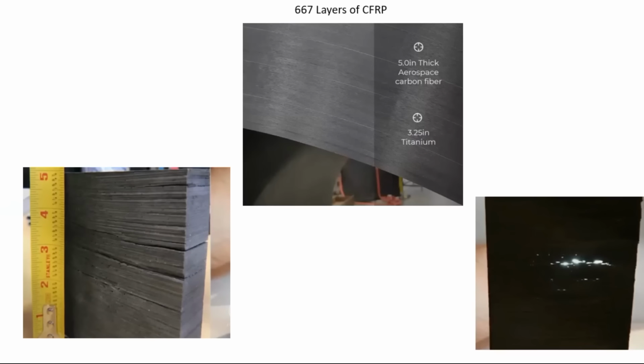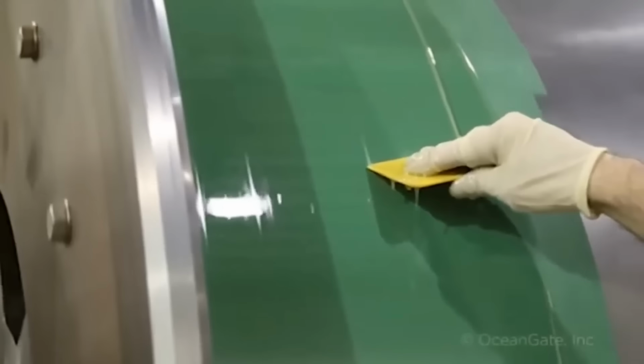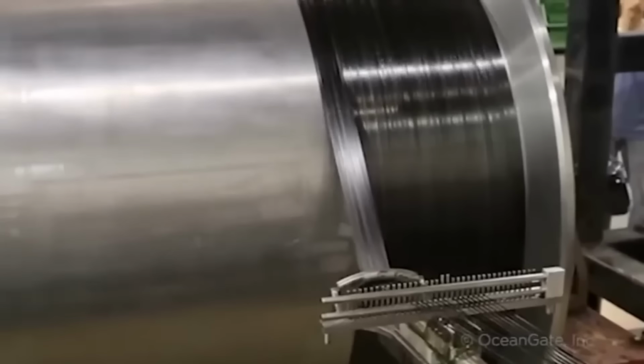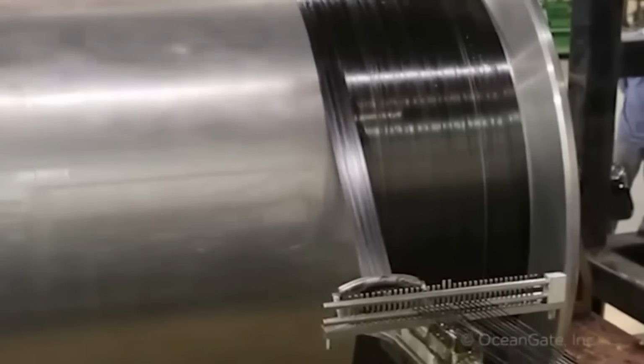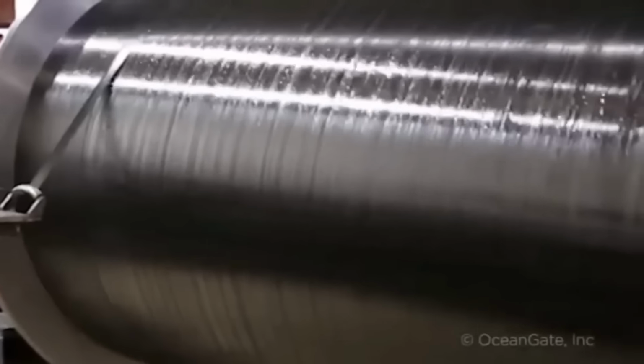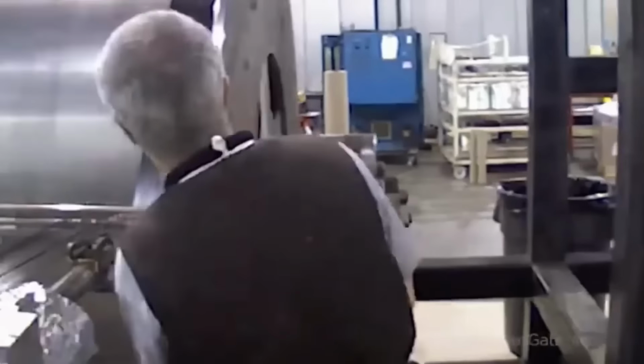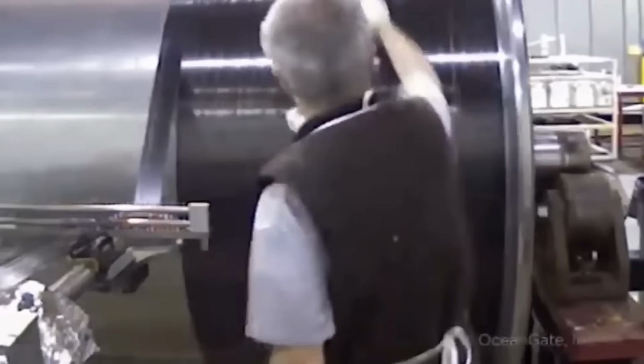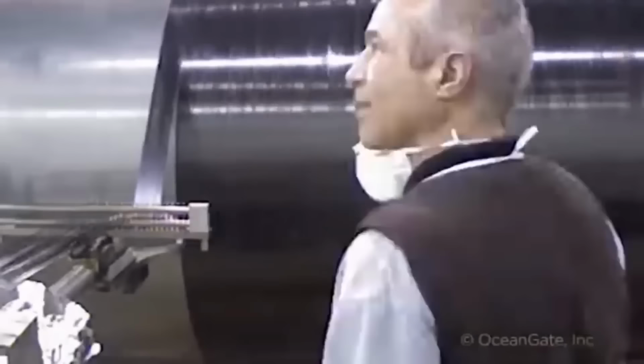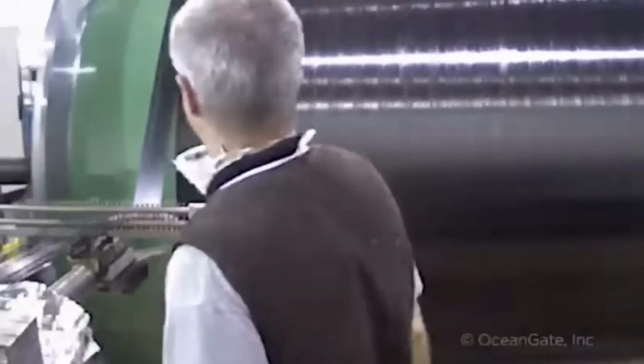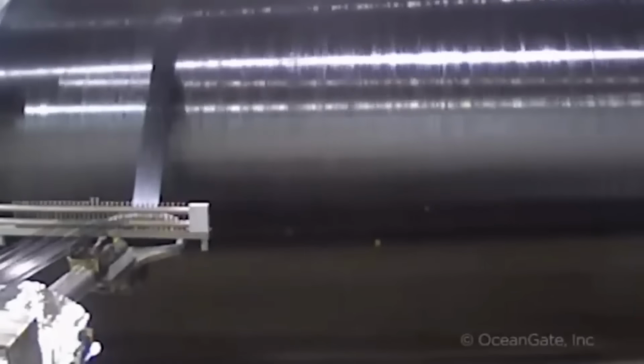The cross-section of the second CFRP cylinder has 667 layers of CFRP and is 127 millimeters thick. The manufacturing process of the CFRP cylinder works like this. A mandrel, which serves as the core around which the carbon fibers are wound, is prepared. The mandrel can be made from various materials, including metal, plastic, or even dissolvable materials if the mandrel is to be removed after curing. The filament winding machine is set up, which consists of a rotating mandrel and a fiber delivery system.